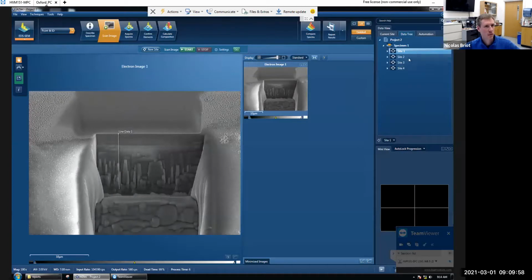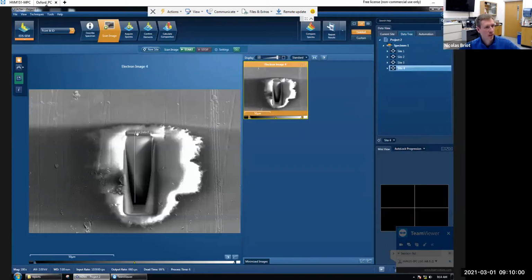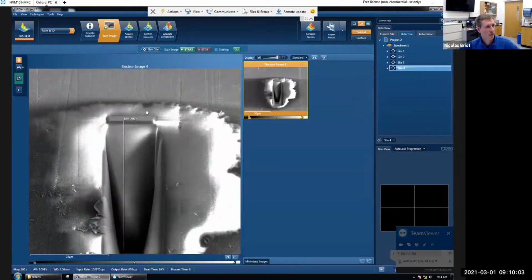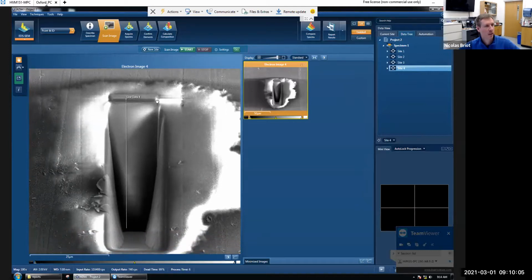All right. So I think this one was good. I went quite deep. So if you can see what's happening here, this is the initial surface of the rod, and I protected the surface a little bit by depositing some material in the chamber. We'll come back to that maybe if we do a FIB cross section today. And then I exposed the cross section. So this is just perpendicular to the surface. Okay, and then I did a line scan from the top. There's a carbon pad protection rectangle here, but then you can see the whole profile here.